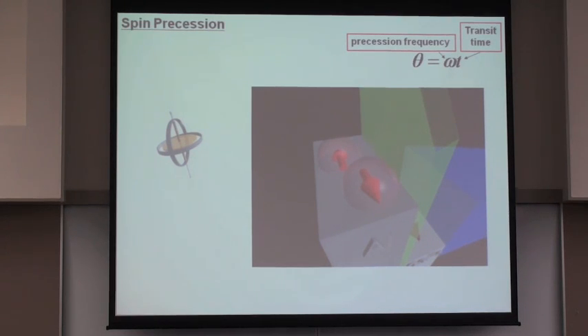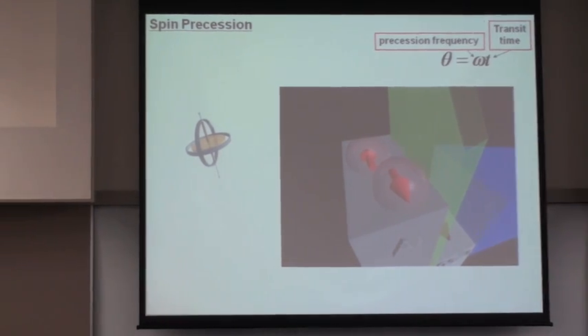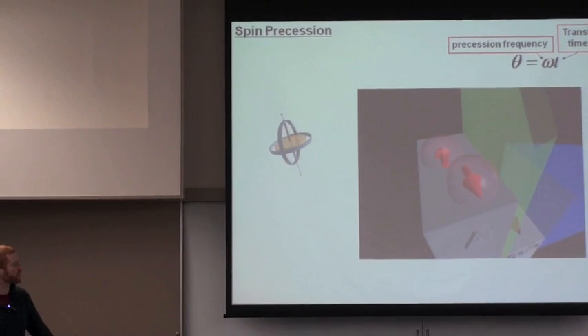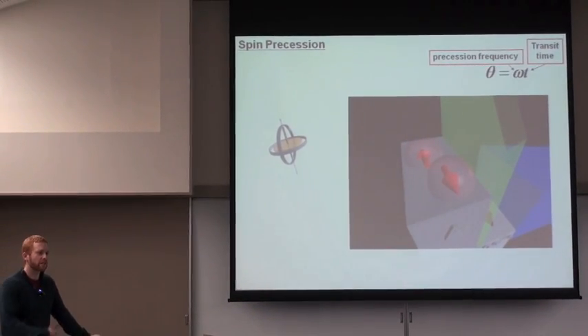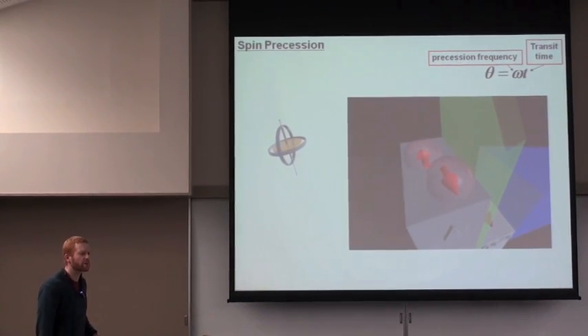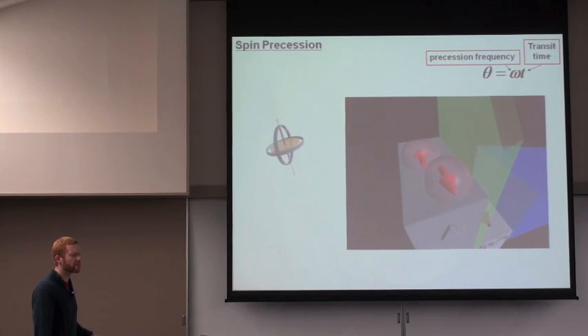So previously what I showed you is that if you change the magnetic field in the device plane, we can switch the magnetization and the relative magnetization between the injector and detector spin axis. And we can see the result. Obviously, when we have a parallel injector and detector magnetization, we have a high spin signal, and when they're anti-parallel, we have a low spin signal.